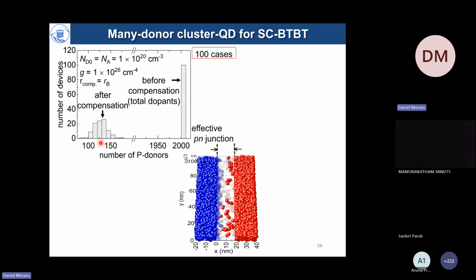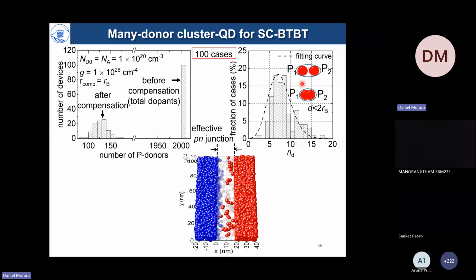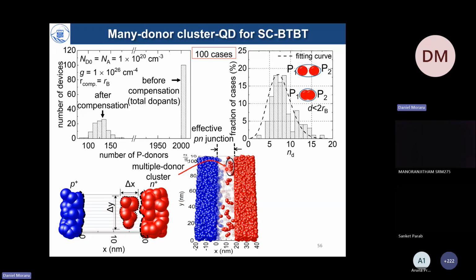So these donors are now redistributed randomly, and we are monitoring the type of molecules that they form. So you can see here how many donors are embedded into each of these molecules. Based on the fraction of cases, this histogram shows that 5 to 10 donors could be a reasonably good quantum dot that can operate in the following way. It's a stepping stone for the electrons starting from the N lead, moving towards the P lead for band-to-band tunneling, while this is filtered to the level of single electron tunneling.